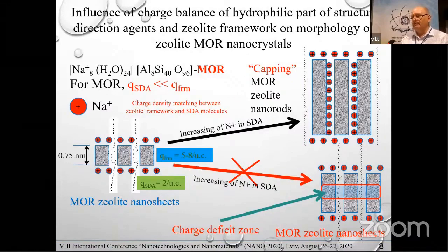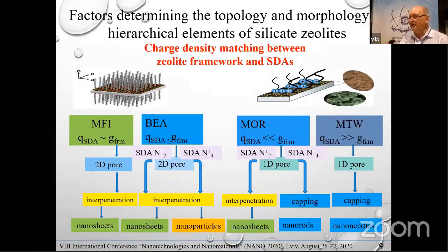The type of morphology of such nanoparticles depends on the mechanism of formation of nanocrystals and on the correlation between the structure of the template and the chemical composition of the zeolite, which can form in such reaction media. There are two different mechanisms. It's the so-named capping mechanism, in the case of covering of nanocrystal zeolites by molecules of template, or interpenetration. In this case, there can be interpenetration of molecules in the micropores of nanocrystals. Depending on the mechanism of formation, nanosheets, nanoparticles, nanorods, or sometimes nanoneedles can be formed, nanocrystals which agglomerate into a large porous substance.